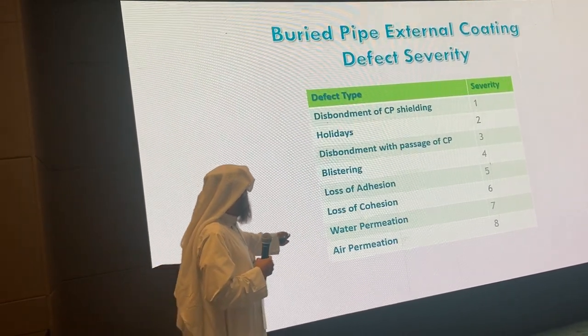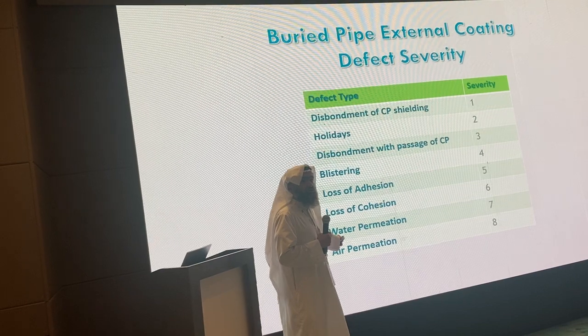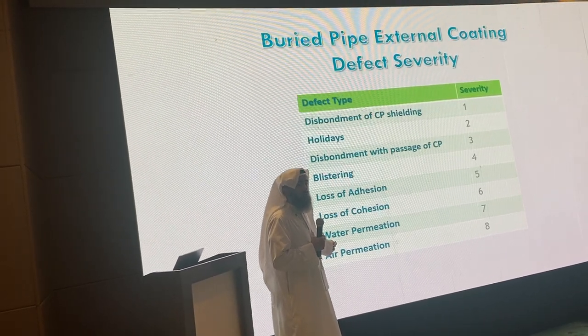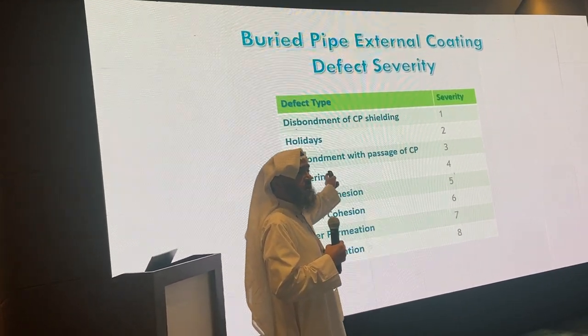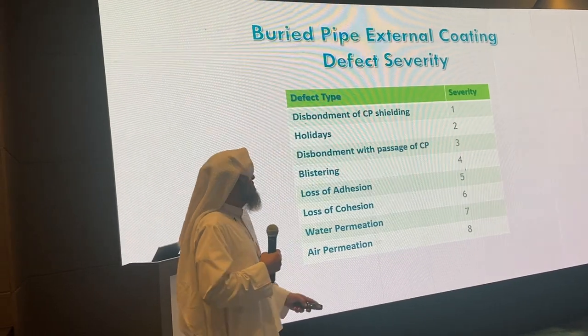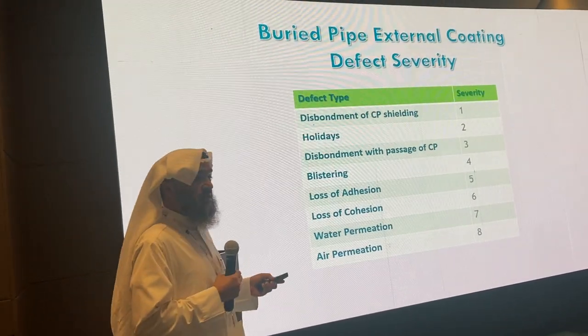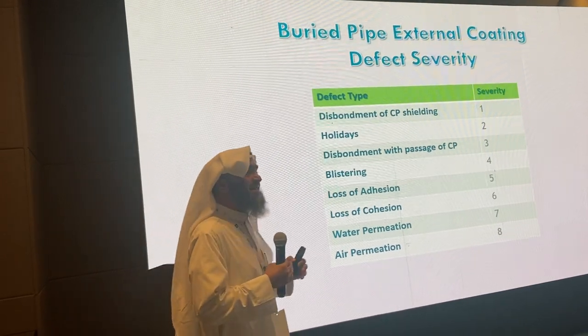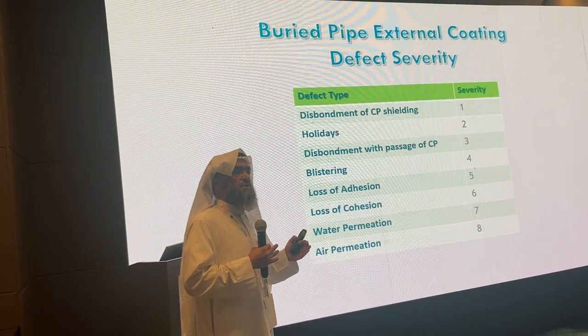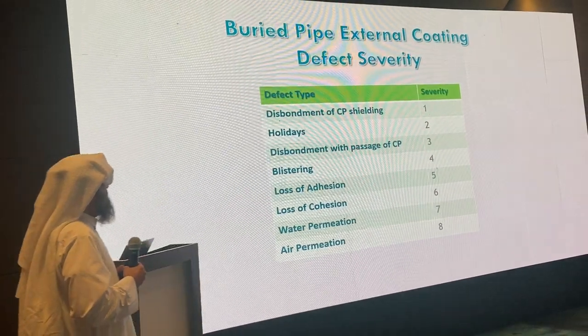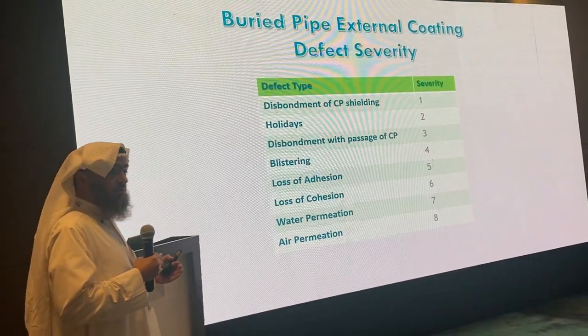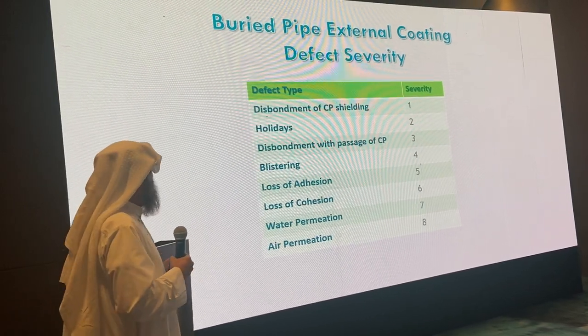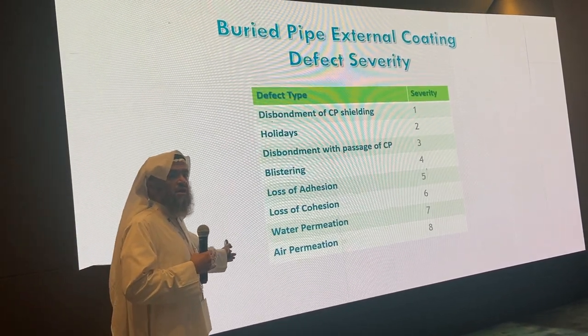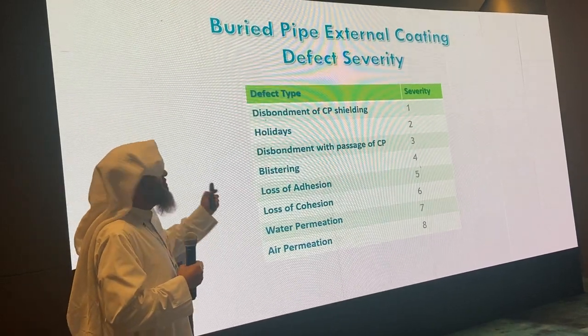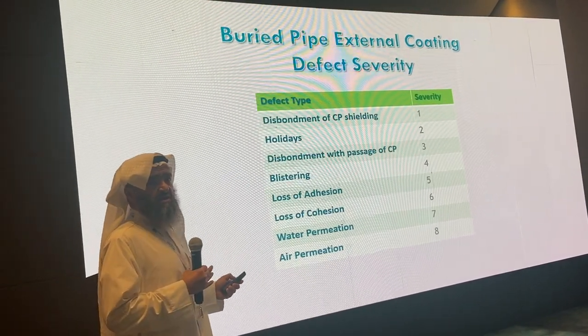We used to think that water permeation is the main cause of corrosion, which is not actually. The main cause of stress corrosion cracking in general and localized corrosion is disbondment with CP shielding. Second is holidays. Third is disbondment of coating that gives little CP passage. Then blistering, loss of adhesion, which is very important, loss of cohesion. Then last is water permeation and air permeation. And by the way, all of what I'm talking about, I took from articles that I can provide you with.